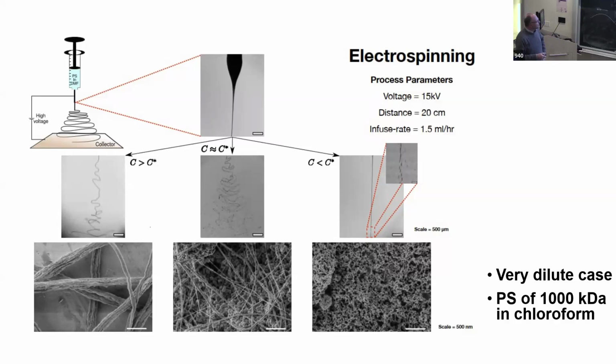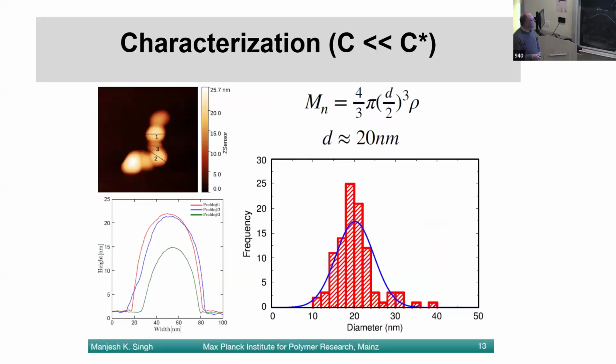And concentration, you see that this very fine jet for concentration here in the solution, which is below the overlap concentration of the chains, this jet breaks into very many small droplets, and what you have here are little spheres of particles. When you analyze the spheres, you see typically that one sphere only has one chain. So there's a little sphere with one very long polymer chain, and this polymer chain is collapsed extremely fast, but it didn't have a chance to entangle.